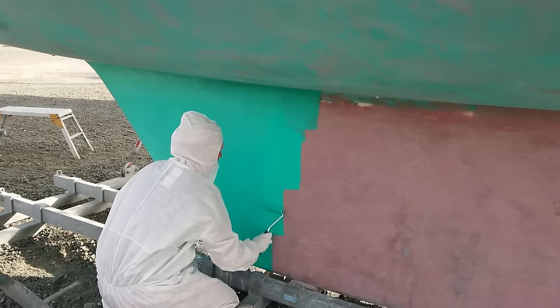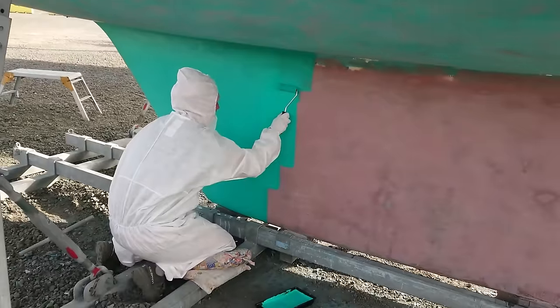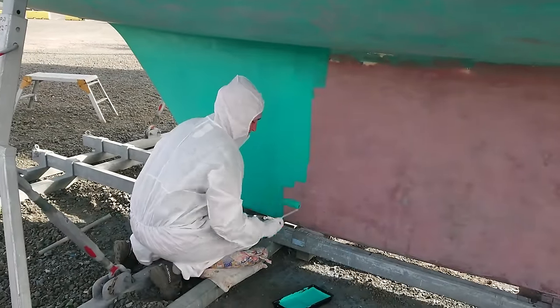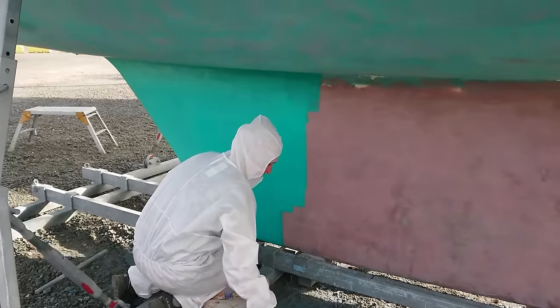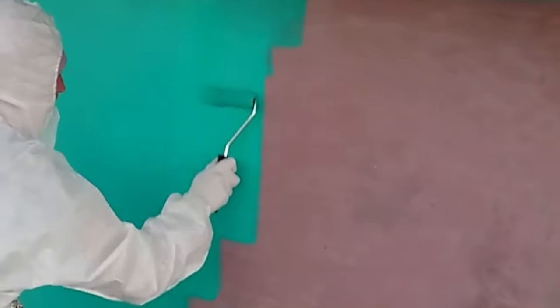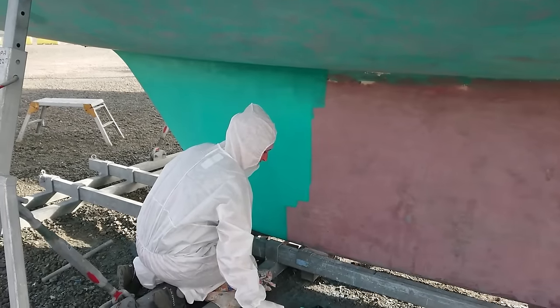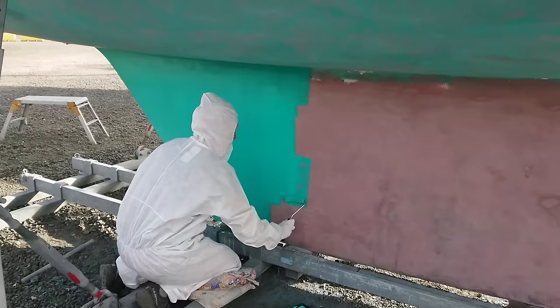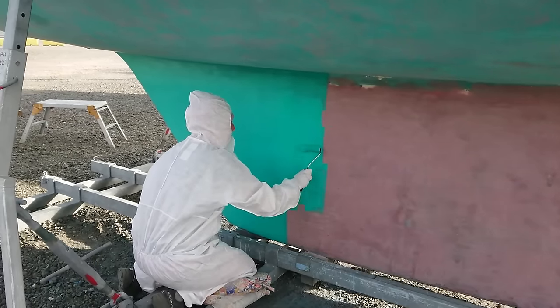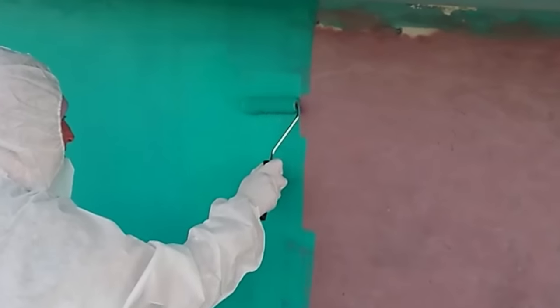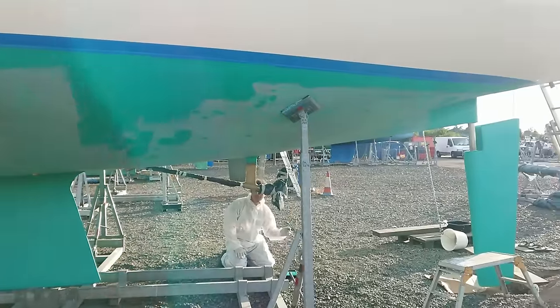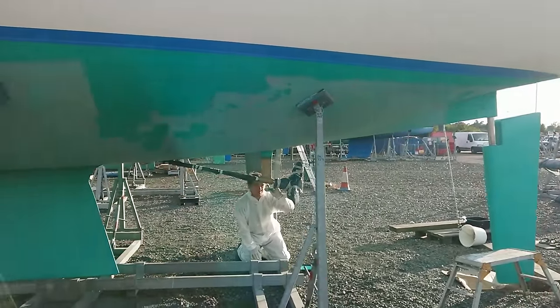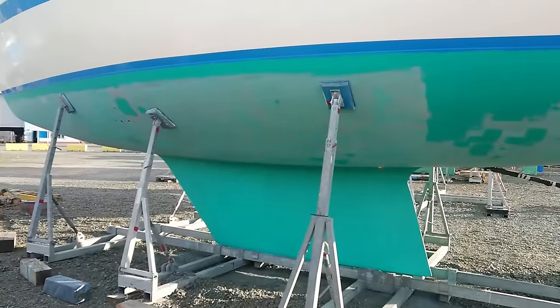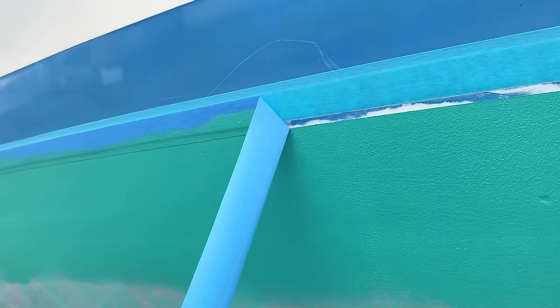So, you may well ask, why on earth are you barrier coating a lead keel that's already faired with epoxy, and you're going to be putting an epoxy-based coating over the top of it too? Well, this is because as you mix the fairing compound, you introduce air into it, and even though I tried to eliminate this, it still will be susceptible to some pinholes from small bubbles. And I know that these unfilled pinholes will cause the copper coat to blister. So, as the barrier coat's quite thin, this will hopefully fill in these holes, and means I won't have to drill and fill any pinholes that might otherwise appear in the copper coat.